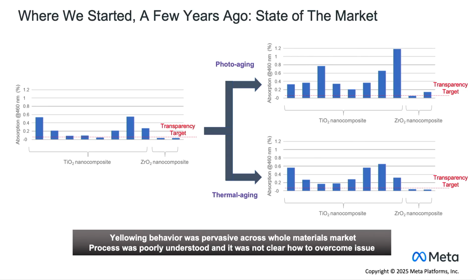So the state of the field back then turned out to have this issue as a general type of behavior, right? If I take here, for example, a sample of commercial and R&D sources in the market a few years ago, we see that if we photo-age them or thermally age them, these are nanoparticles from many different suppliers, many different types of chemistries, all of them lead to yellowing and scattering way beyond what is needed for a stable and efficient AR device. So clearly the yellowing and degradation behavior was very pervasive across the market, and the process was poorly understood. It was not clear how to overcome this issue because, of course, if you look at the literature, everyone's trying to publish their best photocatalyst. No one's trying to make the worst photocatalyst in the world, right?